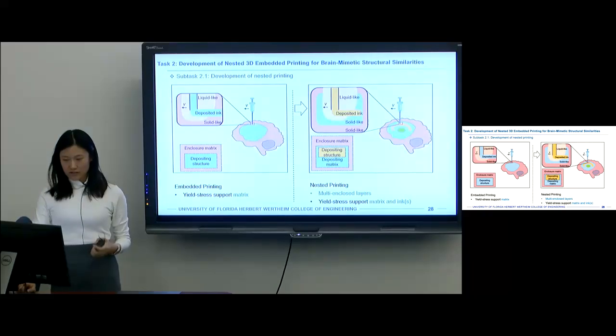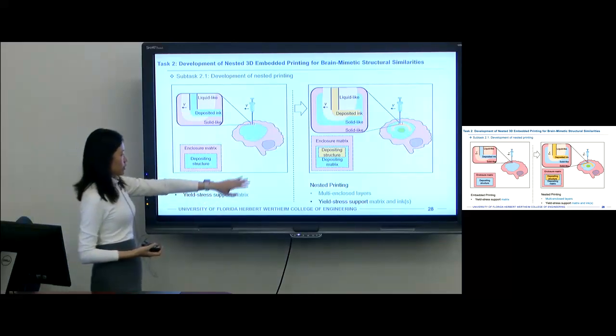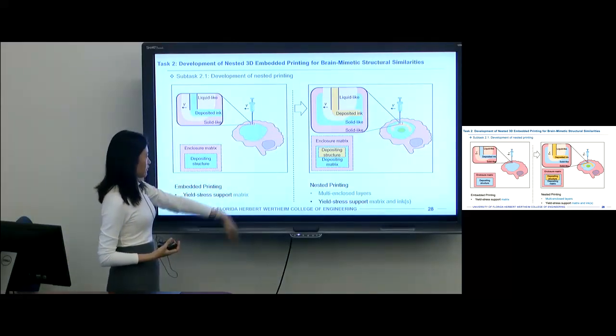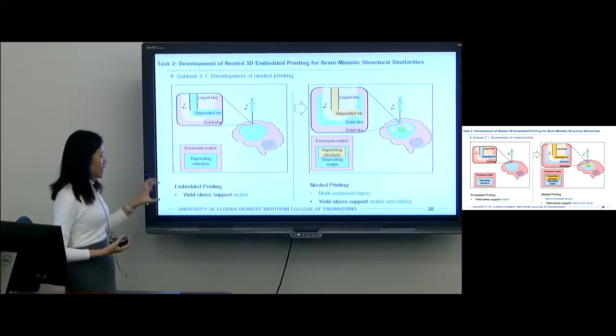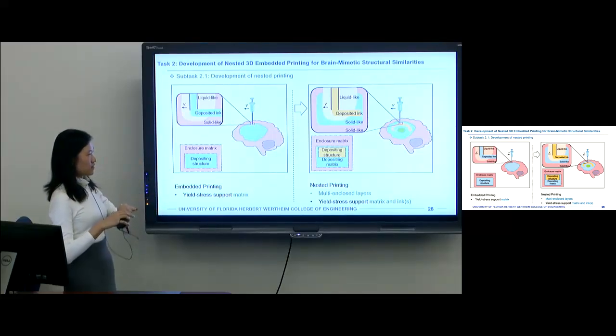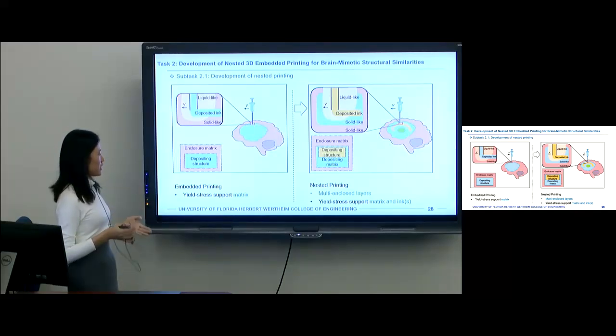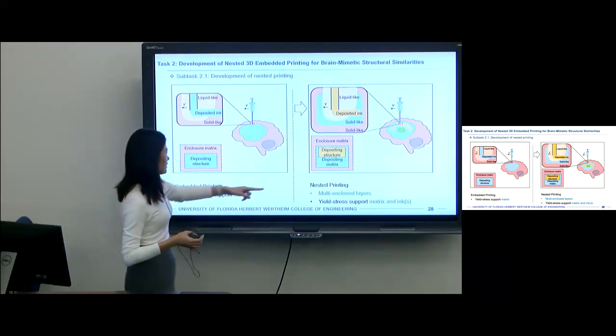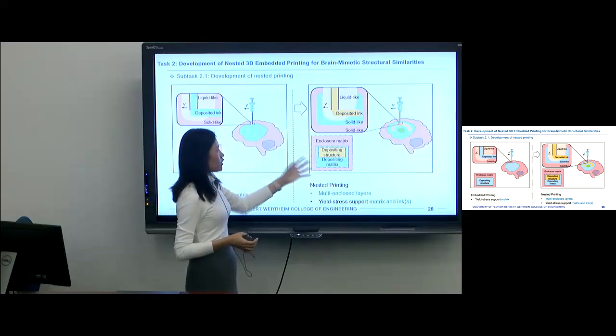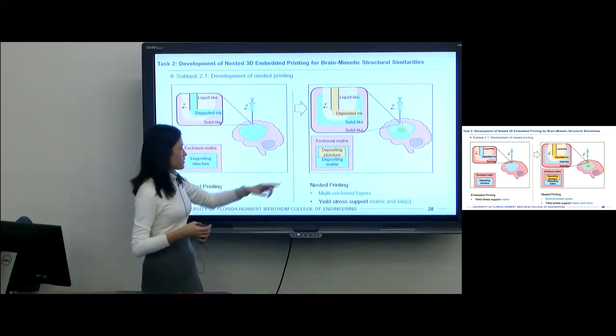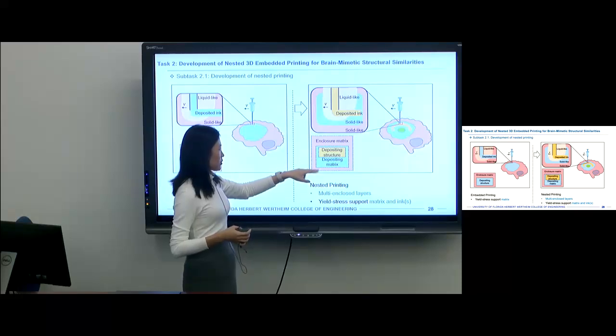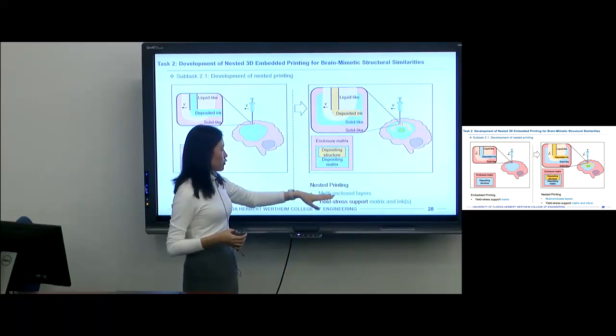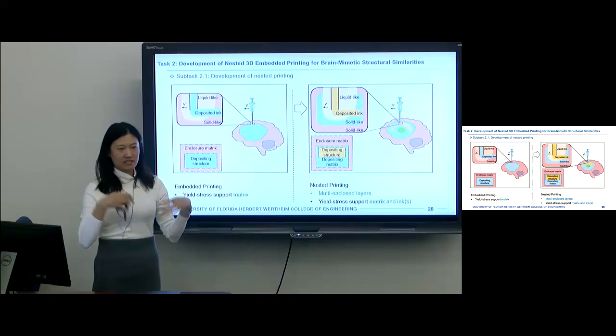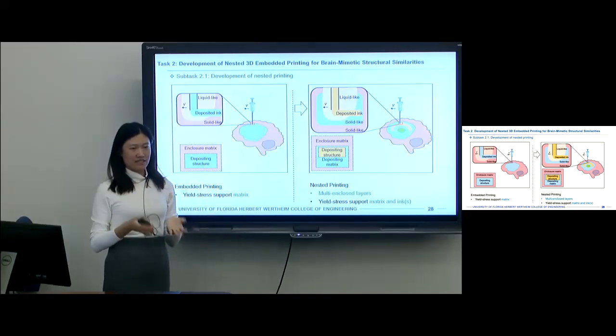To compare the difference between embedded printing, which is the traditional way, and nested printing, which is an advanced way of embedded printing: the similarity is that both methods need a support base and require it to be yield stress. The difference is that nested printing will deposit the structures inside of the pre-existing, pre-deposited structure, so it can form multi-layers if we keep depositing the material into the pre-deposited structure.